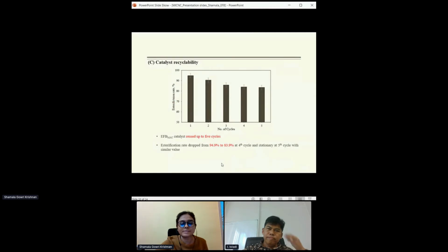Lastly, part C is the catalyst recyclability. The magnetic catalyst was able to be reused up to 5 cycles with a reduction in the esterification rate to 83.9% at the 4th cycle, and it remained at a similar value at the 5th cycle. It is worth mentioning that the catalyst was still able to be separated magnetically.